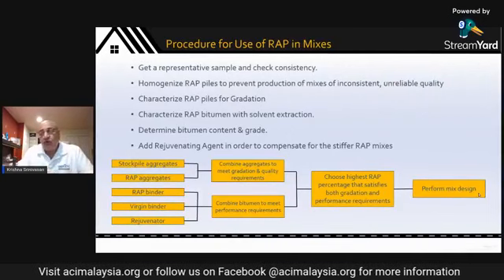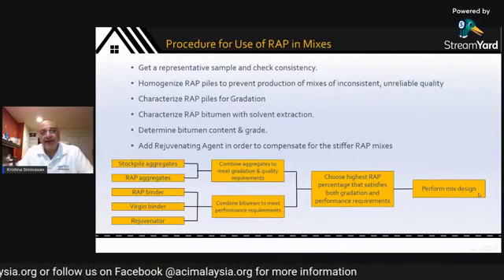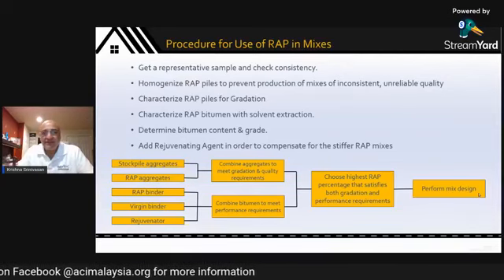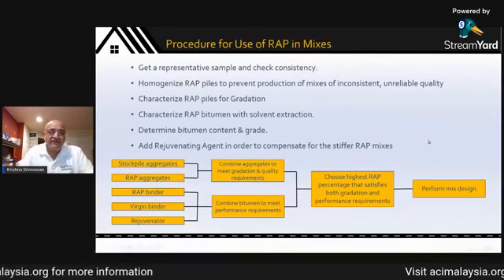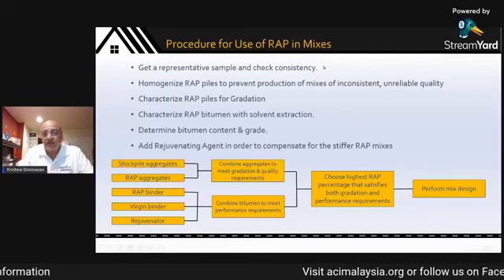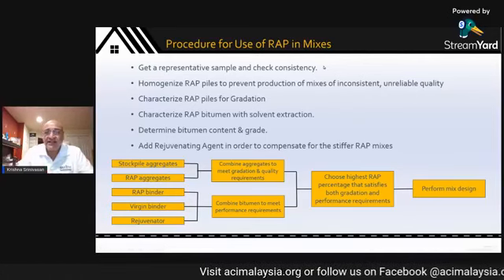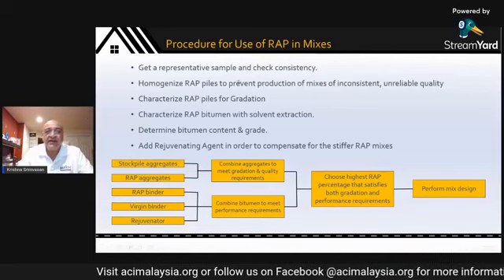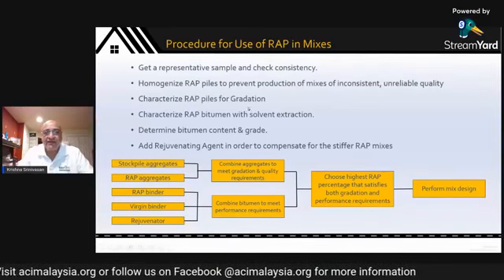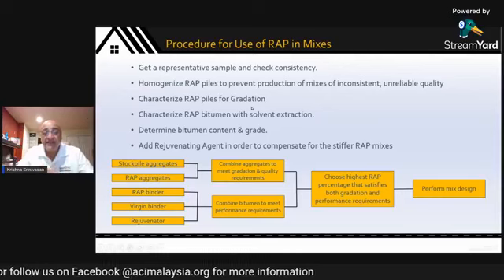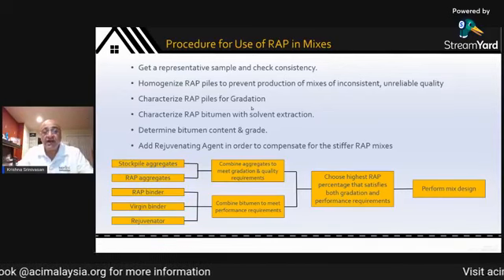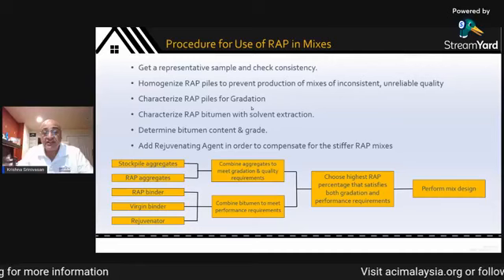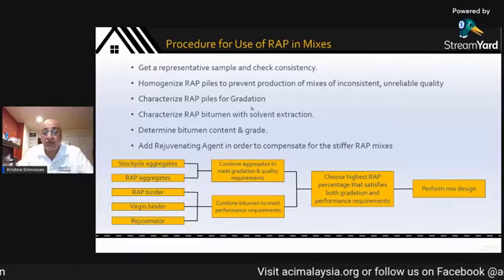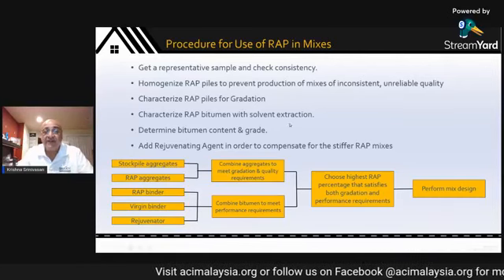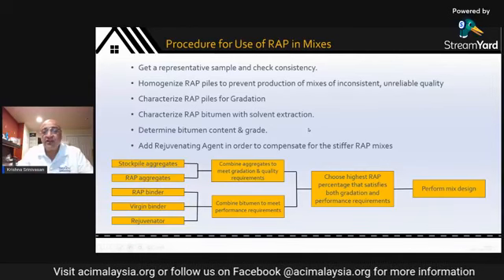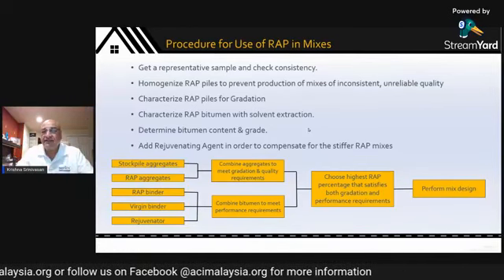So how do you go about incorporating RAP in a mix? Again, very simple scientific principles. You get a representative sample. You check for consistency. You keep homogenizing the piles so as to, as I said, get a consistent material. You characterize the RAP material for both gradation, which is particle size, as well as your bitumen content. What is the bitumen content? How much is there? What is the grade? What is the quality of that bitumen in the RAP, etc.? You add a rejuvenating agent in order to be able to compensate for that stiffness.